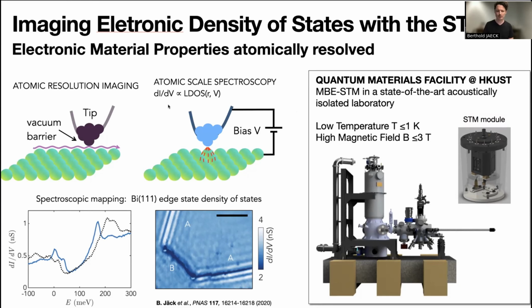How this works is that we apply a small bias voltage modulation between the tip and sample, and then study the differential tunnel conductance. It turns out that this dI/dV signal is directly proportional to the local density of states as a function of energy, which maps directly to the applied voltage. Neatly, when we fix our applied voltage to a specific value, for example, here to this peak, we can then map out the spatial distribution of this dI/dV amplitude.